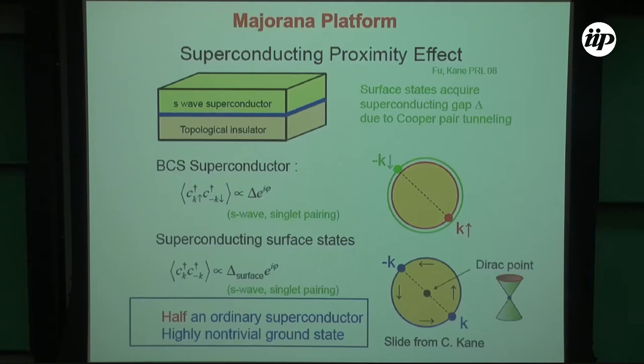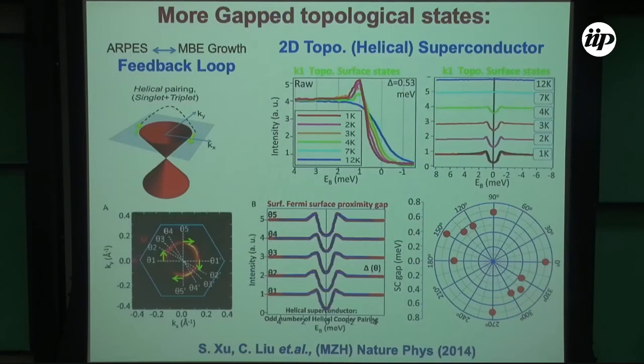We can do spin and momentum and energy. All we have to make sure is that we have half the degrees of freedom. In other words, whether the system has half of an ordinary superconductor. That is already fixed by this, because there's no other Fermi surface there. This is a half Dirac gas. And since this gap opens only on this Fermi surface, it's half of an ordinary superconductor, even though